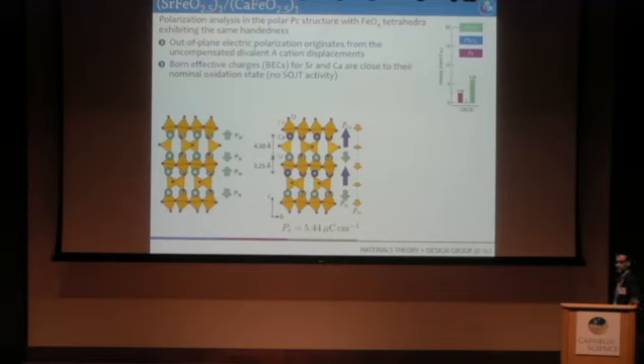As soon as I chemically order this thing, as you might suspect, calcium and strontium are going to displace by a different amount, and this will lead to a polarization along that B axis in this structure. The added effect of having these tilts or the shearing of the octahedra is I do have iron displacements that occur in the plane. The space group's monoclinic.